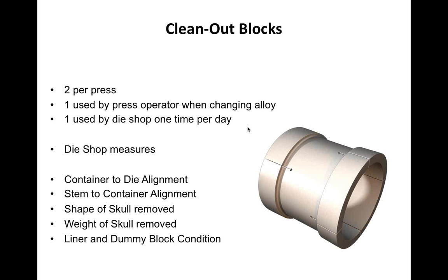Next, he runs the cleanup block and visually looks at the skull that's removed on the front of the block. If it's a tiara, which means it's skewed to one side, he understands that the stem, the container alignment isn't accurate. If it's concentric and nicely formed, then he knows that the stem, the container alignment is quite good. Then he'll weigh the skull removed from the liner, and again on a 8-inch diameter billet by 40 inches long, we would like to see about a pound of skull removed. If the weight is above this, typically it means that the liner is bellied and we're entrapping more aluminum than we want. If the weight is less than this, typically the dummy block is plastically deforming and we're leaving inadequate skin thickness on the liner.